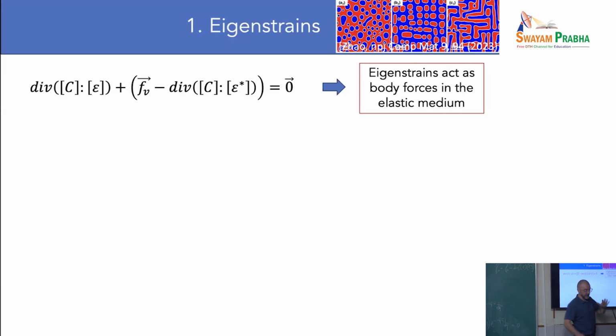But the eigenstrain is not just a change of lattice parameter. It's a bit more complicated, and so you have regions where the elastic interactions are weaker than other regions, and that breaks the symmetry of the precipitates and gives you these elongated precipitates. Do I make sense? Yeah. So you see, you suffered, but now you know what is behind these phase field simulations.